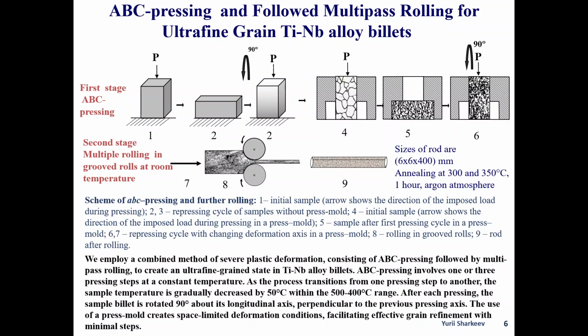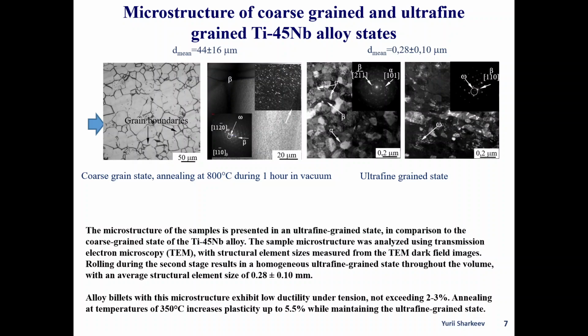The use of a press mold creates space-limited deformation conditions, facilitating effective grain refinement within minimal steps. The microstructure of the sample is presented in an ultrafine grain state in comparison to the coarse grain state of the titanium niobium alloy. The sample microstructure was analyzed using transmission electron microscopy with structural element size measured from the TEM dark field images. Rolling during the second stage results in a homogeneous ultrafine grain state throughout the volume with an average structural element size of 0.28 micrometers. Alloy billets with this microstructure exhibit low ductility under tension, not exceeding 2 to 3%.